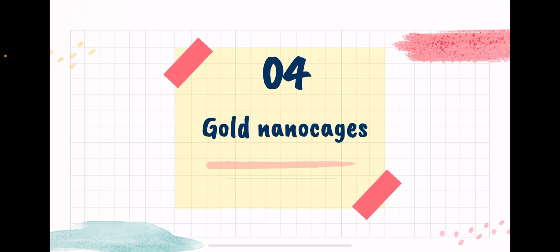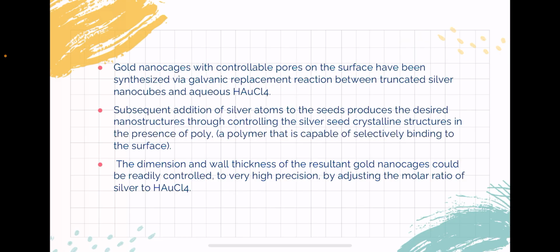The fourth type, gold nano cages, it's a hollow مجوف يعني porous gold nanoparticle ranging in size from 10 to over 150 nanometers. They are created by reacting silver nanoparticles with chloroauric acid in boiling water. The dimension and wall thickness of the resultant gold nano cages could be readily controlled to very high precision by adjusting the molar ratio of silver to this solution.